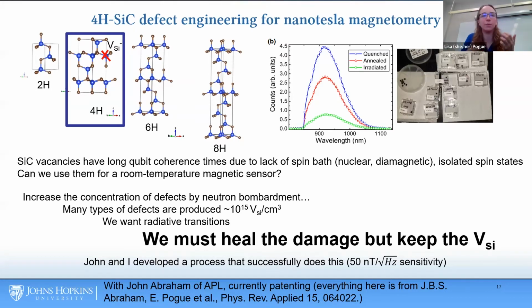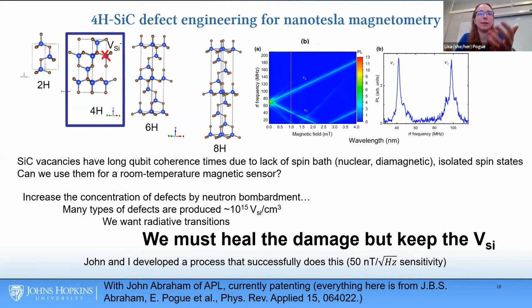And through that process, we were able to get sensitivities of 50 nanotesla per square root hertz, which was an improvement upon what had been reported for silicon carbide before. Because silicon carbide is much easier to process than diamond and integrated devices and has shown electroluminescence, this could be very useful for devices. And you can see here that with very small fields, we're able to see a radio frequency shift that is proportional to the strength of the field associated with those silicon vacancies.